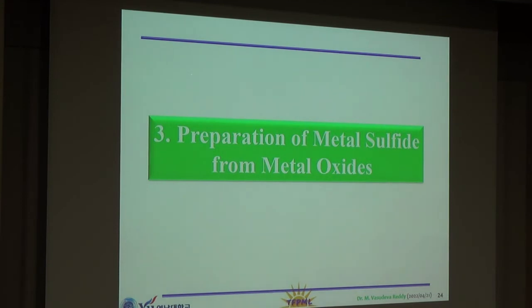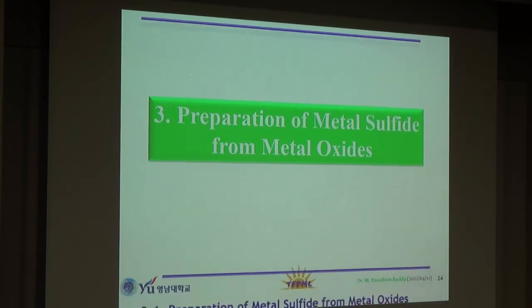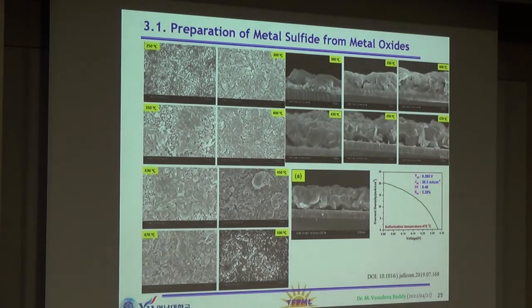Now I am going to discuss how to prepare the metal sulfide from metal oxides, and why should we do this process. If you look at this picture, we prepared these tin sulfide films using sputtering and sulfurization process. There the metal layers were deposited first using sputtering and then sulfurized. If you look at these 2 pictures, you can find a lot of pinholes and a non-uniform surface.